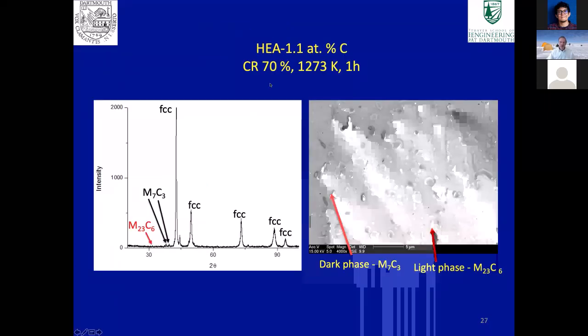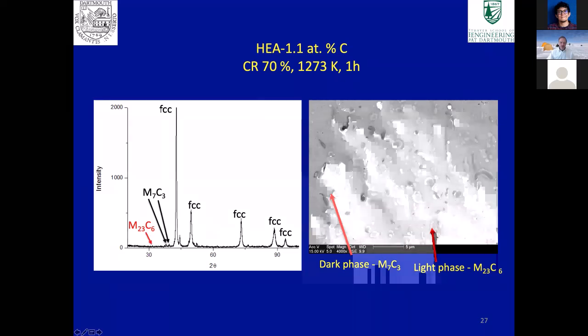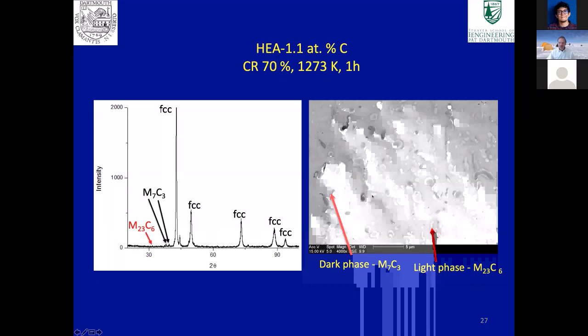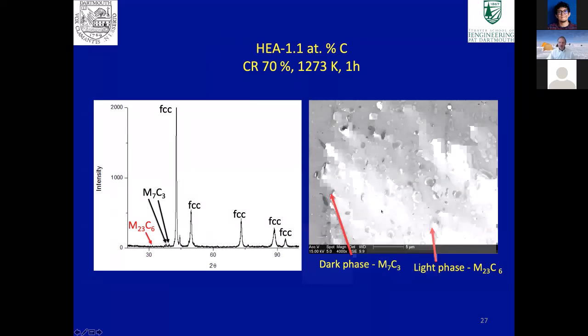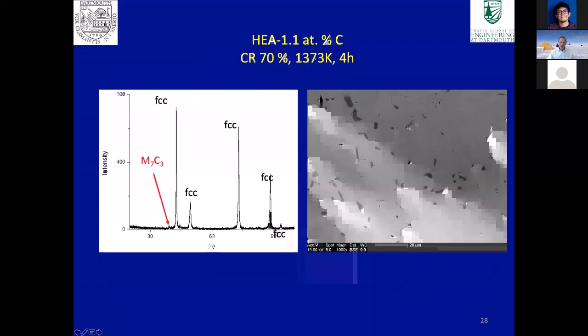Turning to the carbon-doped alloy, you can see we can identify two different types of precipitates at this temperature of 1273 Kelvin. And if you look at the microstructure, you can see dark precipitates and light precipitates, which correspond to two different kinds of carbides. If you go to a higher temperature, you only end up with the M7C3 type carbides in the structure. Just these dark ones are there after that.